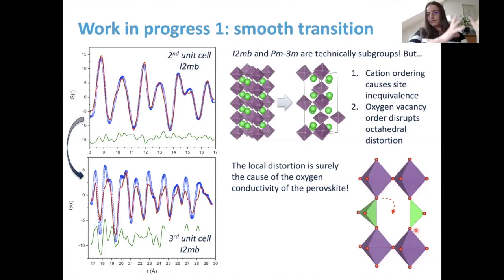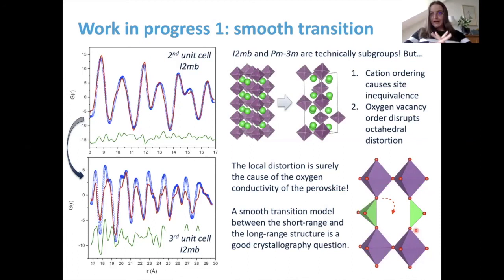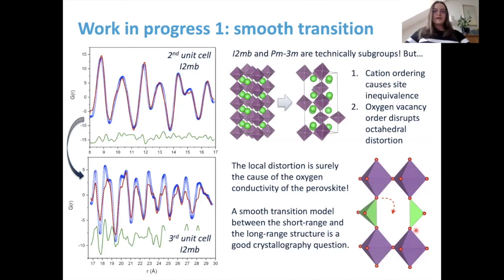Within a mechanical distortion using group-subgroup relationships, the distorted phase should still have its oxygen. I haven't found an elegant way to handle this yet, but there must be a smooth way because the structure is showing you one — an average cubic sample with properties that evidently come from a brownmillerite at the local scale, providing space for oxygen to jump around and get from one side of the structure to the other. The smooth transition model is my current goal.